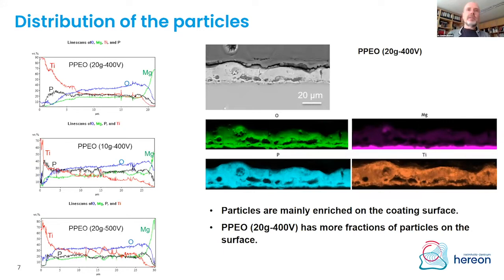You can see it nicely in the cross sections. On the left, you see line scans, and on the right side, there is the cross section of a coating produced at 20 grams per liter anatase addition and 400 volts. And what you clearly see, if you compare the 400 volts and the 500 volts at 20 grams, is that you can keep more concentrated titanium dioxide particles on the surface. But that I will show you in the next slide.